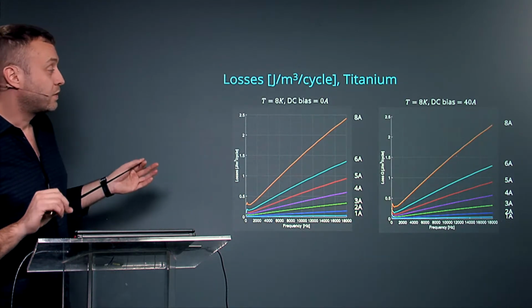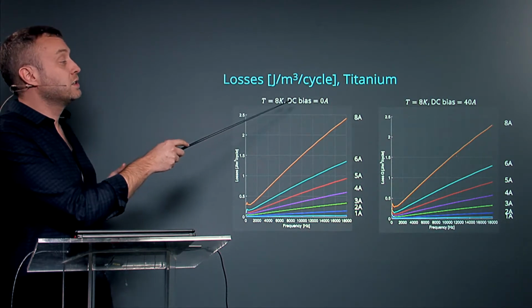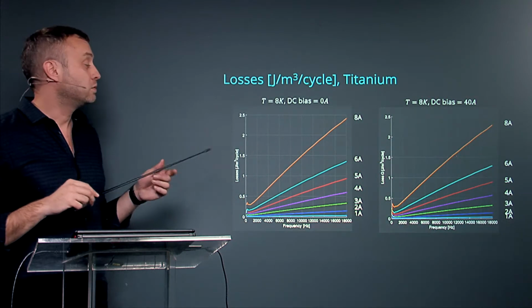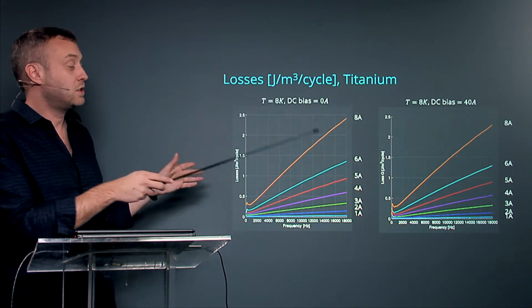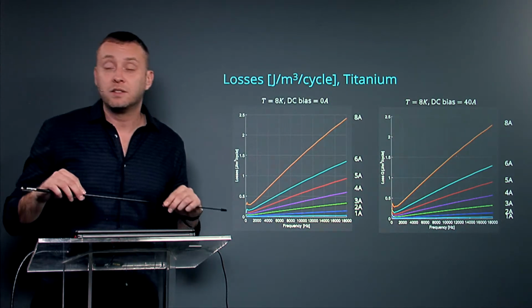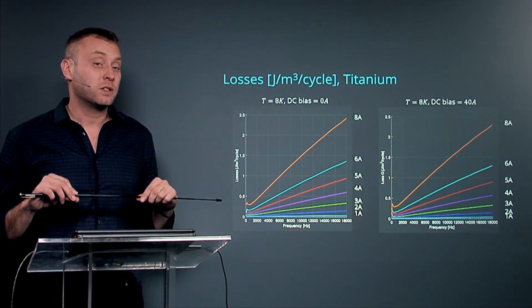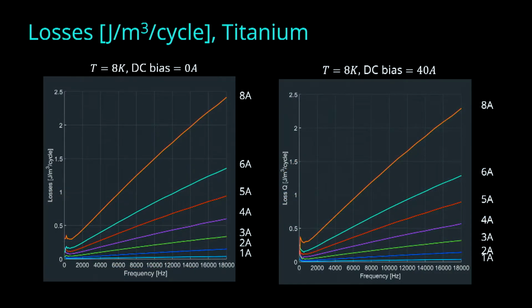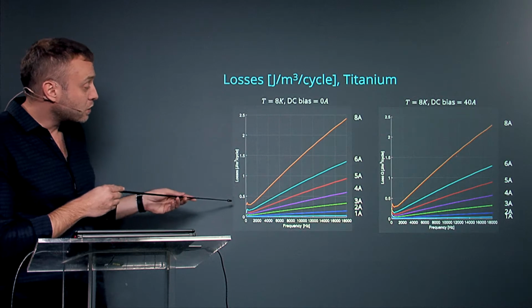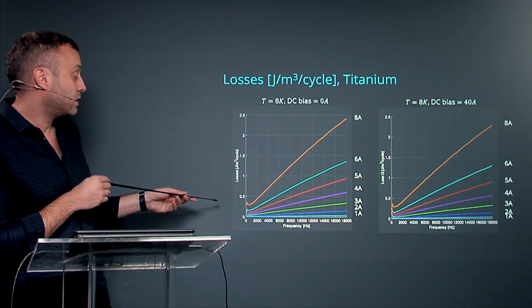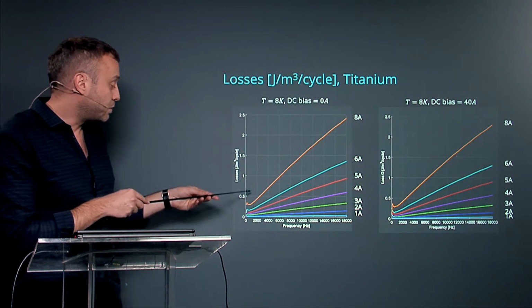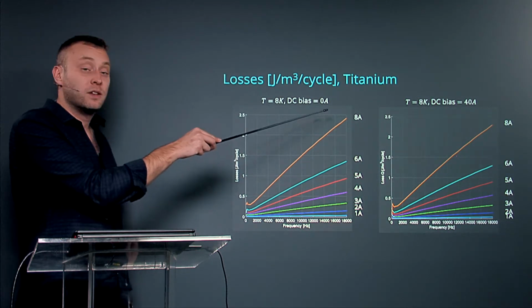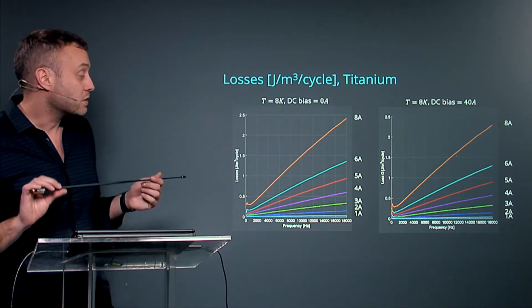is this. First of all, the DC current does not affect the energy loss at all. The graphs are the same. As we know, DC current does not produce energy losses in a superconductor because there is no change. So only the alternating part would. And this is clearly seen in this example. In addition, we see that for lower frequency, the energy loss is quite stable and constant. And at some point, it crosses over, and then there is a strong frequency dependence for energy losses.